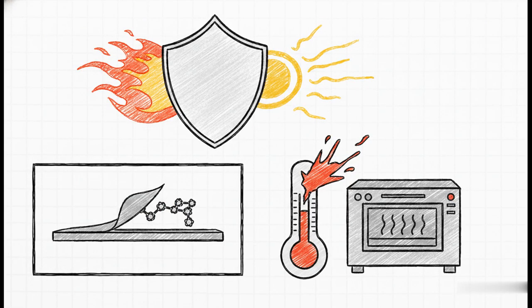But as you've probably guessed by now, our high-heat hero has a pretty major Achilles heel. Yes, it survives 600 degrees and can brush off UV rays for decades, but its ultra-low surface energy gives it absolutely terrible natural adhesion. It struggles to stick to bare steel unless you use specialized silane coupling agents acting as a chemical bridge. On top of that, to fully cross-link, it demands massive baking temperatures, upwards of 250 degrees Celsius. It's an incredible material for sure, but highly restricted by these extreme application constraints.